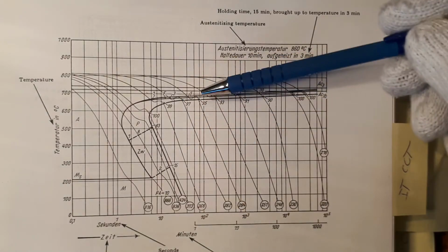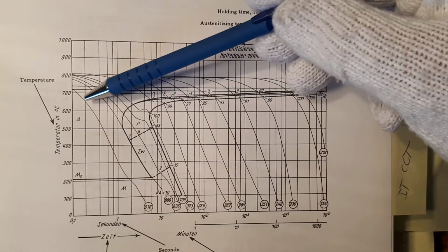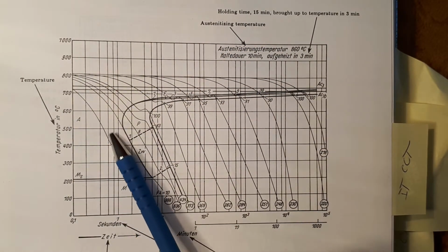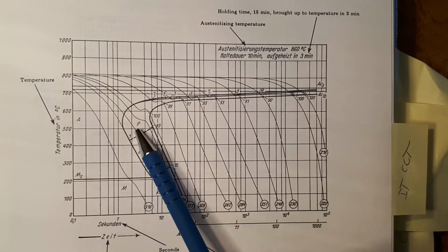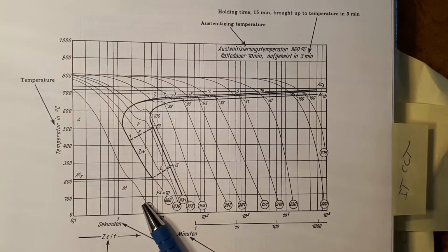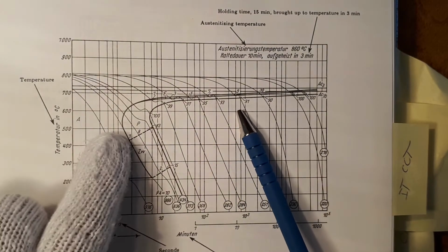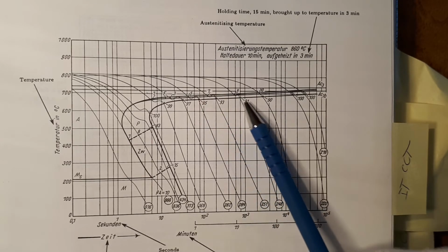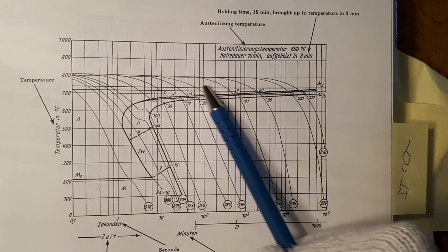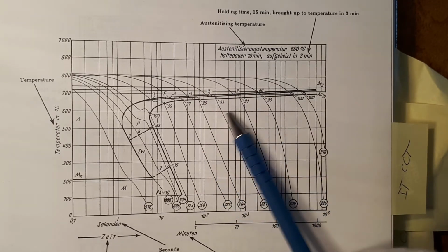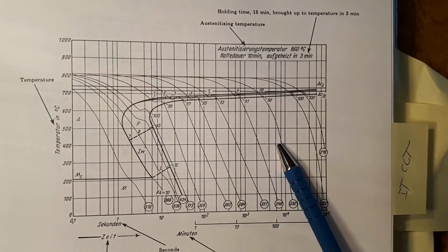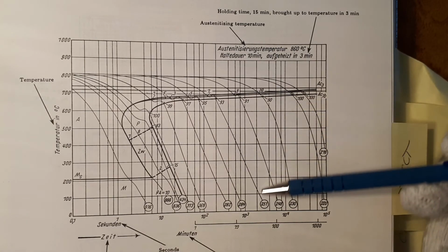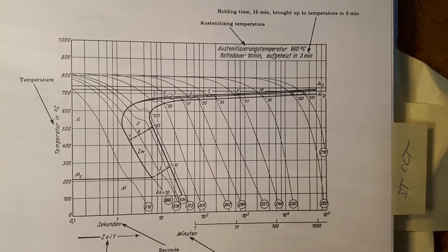These other lines here, these are cooling lines representing the temperatures within a metal which has been austenitized and then quenched. This cooling curve right here passes the nose of the curve, will go straight into martensite. Other cooling curves here do not go past the nose of the curve, and they go across the transformation begins and transformation end lines, and thus forming different microstructures here. This would be an annealing type curve. These cooling rates are best transposed on top of CCT diagrams.